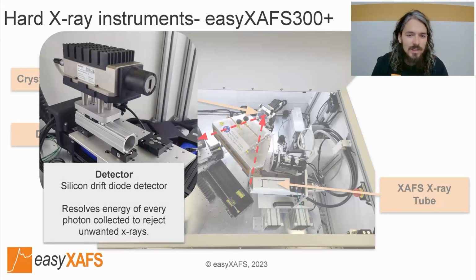For the detector, we use a silicon drift diode. The advantage of using this detector is that it measures the energy of every single X-ray detected to within a couple hundred electron volts. That allows us to pick out the monochromatic beam from the crystal that we want to use for our measurement and separate that from potential backgrounds that we don't want or unwanted harmonics.